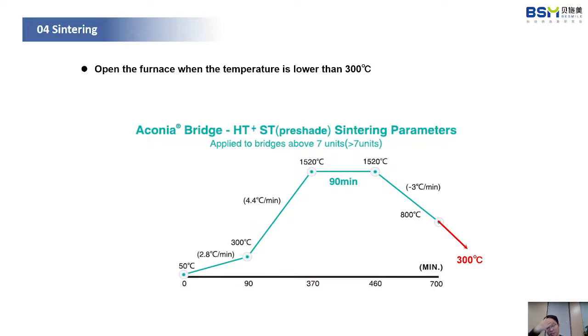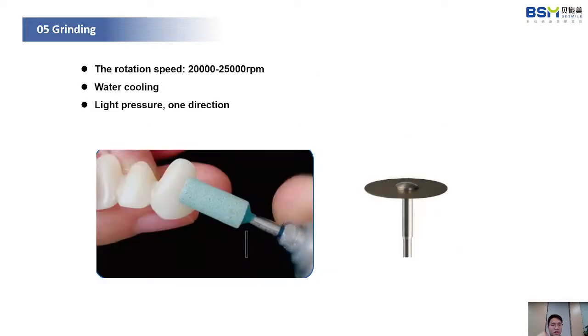comes into contact with cold air, because the restoration is very hot, it may crack because of the cold air. So we recommend opening the furnace only when the temperature is lower than 300, especially in the winter, when the room temperature is much lower. After sintering comes grinding. In this step, the most important thing is the grinding method. We need to do water cooling during the whole grinding process, with light pressure, and grind in one direction.